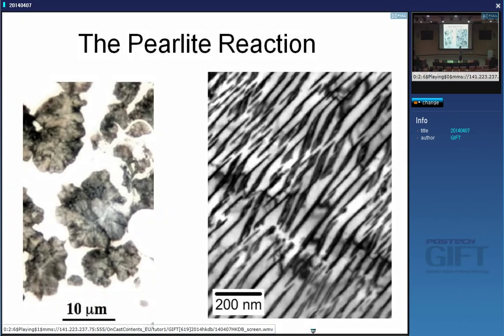But if the spacing is coarse, then on certain sections, you may be able to see the lamellae of cementite and ferrite. And I explained to you in a previous lecture that a colony of pearlite is not really one layer of cementite, another layer of ferrite, and so on, but an interpenetrating bicrystal of ferrite and cementite. So there are only two crystals in here in terms of crystallographic orientation, ferrite and cementite. And what we see when we look at images like these are sections of that three-dimensional structure, so it appears as if we have alternating layers of ferrite and cementite.